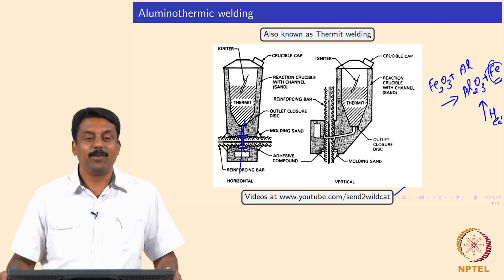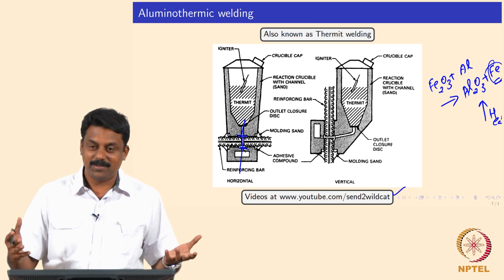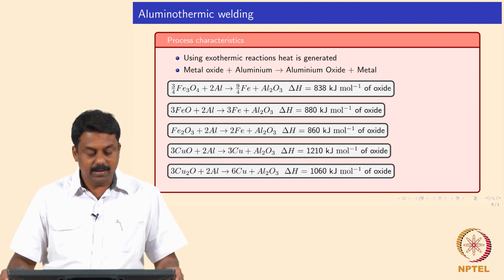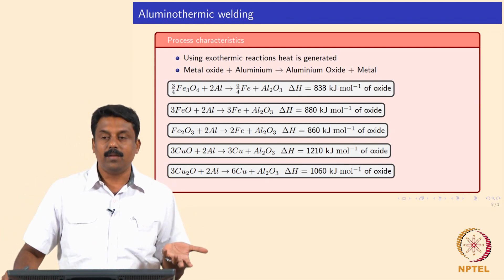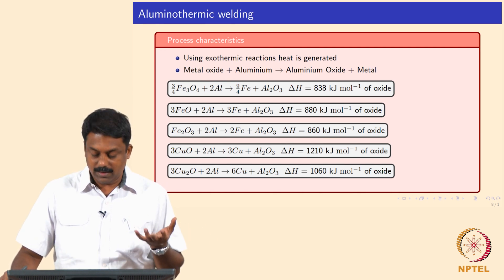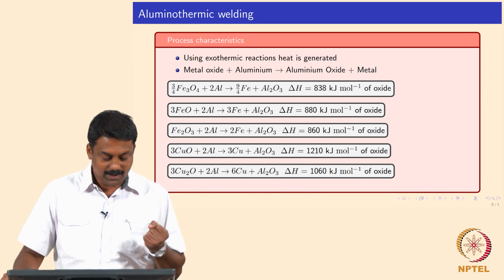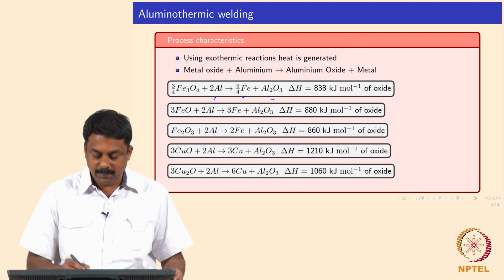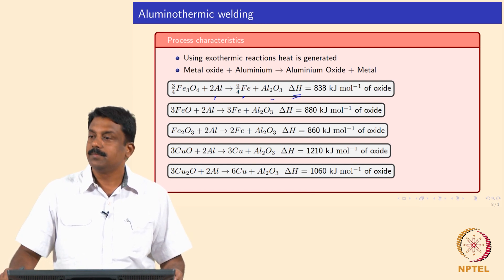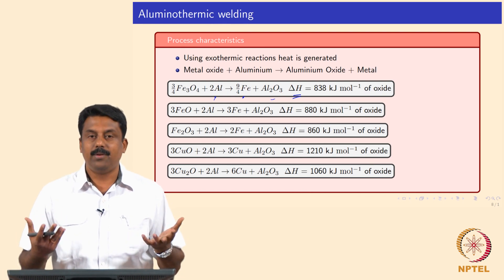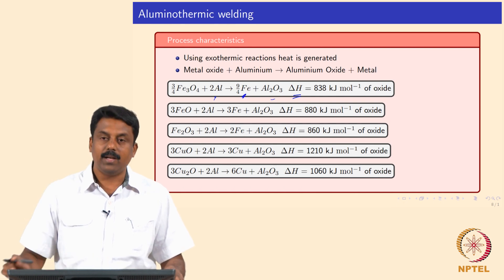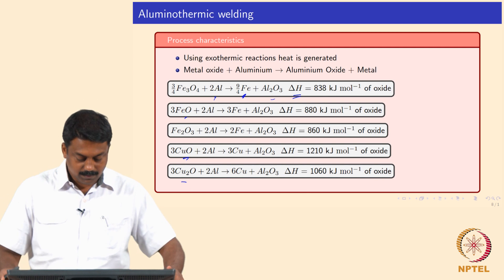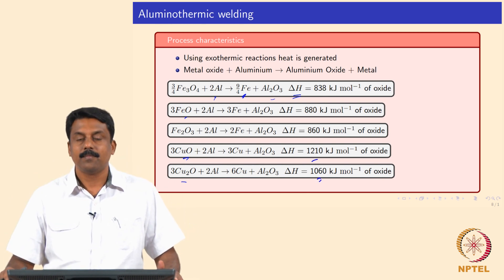You can look at my YouTube page - there are three videos which are very long and you can enjoy them from the beginning. The main principle reaction used is the exothermic reaction when the metal oxide reacts with aluminium, burns, forms aluminium oxide and liquid metal, generating a very high amount of heat. For example, Fe3O4 reacts with aluminium to form liquid iron and aluminium oxide - the enthalpy of this reaction is 838 kilojoules per mole of oxide. That is a huge heat which actually produces molten iron. You can also use Fe2O3, and you can also weld copper as well, with an even higher delta H of reduction.